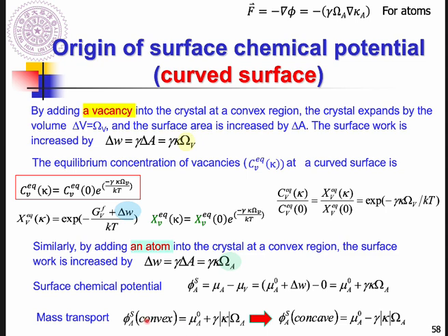So now you have the gradient, right? The driving force is the negative chemical potential gradient. We have gamma omega, and gamma omega is a constant, so the only gradient term you actually have is the kappa gradient. So we have a negative kappa gradient for atoms.